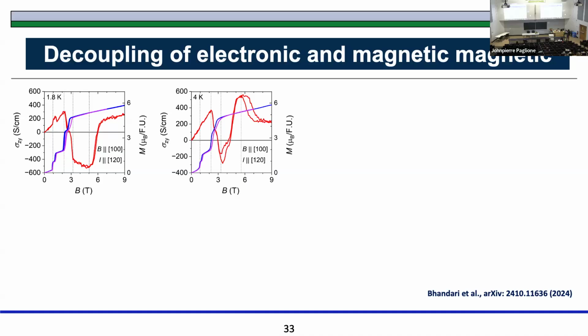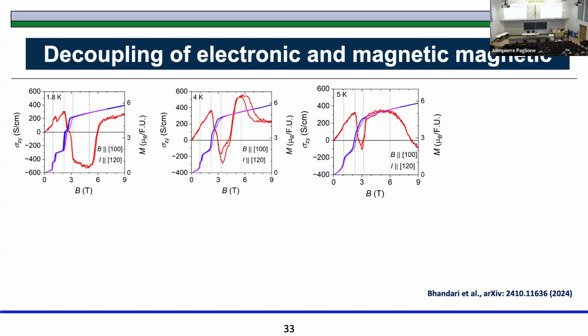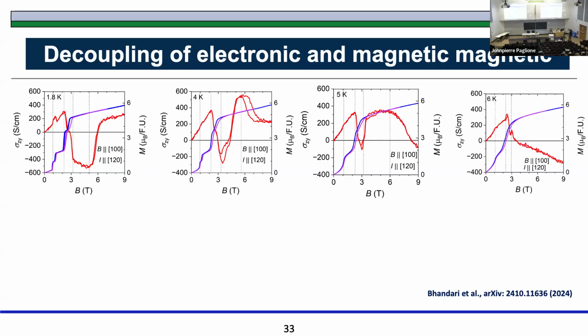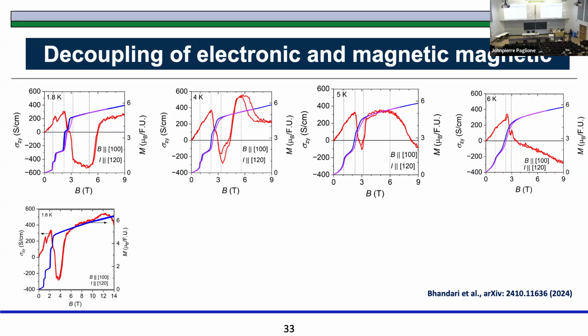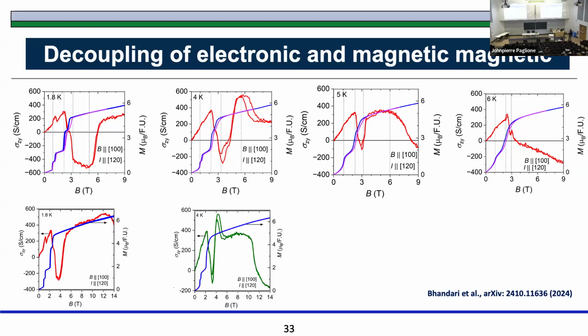It comes towards the lower side temperature. There seems like there is another transition at high temperature, high magnetic field even at 1.8 Kelvin. And then at 5 Kelvin, we still see that, and then it disappears above 6 Kelvin or so. So that low temperature magnetic phase seems to be very interesting. We measured another sample, we put to 14 Tesla. In 14 Tesla, we see this drop at about 12 Tesla, where there is no change in electronic structure, and we can recover the same feature at 4 Kelvin as in the previous sample. So this is something very interesting, and could be a very interesting interplay between your magnetic field and the spin textures. So, maybe there are some very, very degenerate states that don't change your magnetization, but for the electronic structure, that change is good enough to bring all these changes.